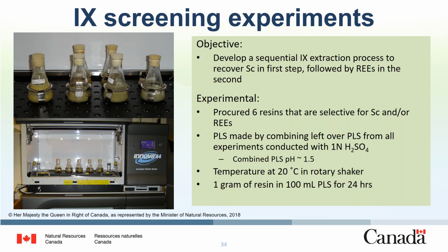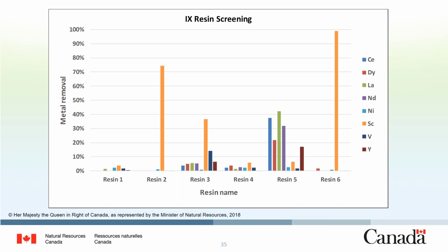The PLS that was used for these experiments was made by combining leftover PLS from the previously described experiments, and that's to really replicate all the conditions. We didn't see much use in using synthetic solutions. Since scandium accounts for more than 50% of the contained value in this material, it was proposed to develop a 2-step IX process where scandium would be removed in the first, followed by the removal of the remaining REEs in the second step. 6 resins were tested in total.